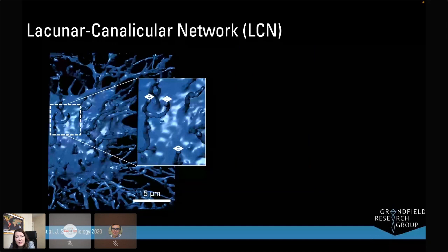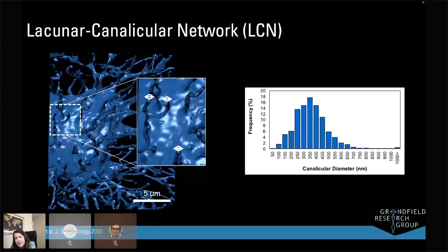Like the size of the canaliculi, and we could perform some measurements on their size. They're around 350 nanometers in diameter, and this is really exciting because most estimates of their size use diffraction-based techniques like X-ray tomography as opposed to direct imaging techniques. So this tool gives us a direct measurement of the size of features like canaliculi.